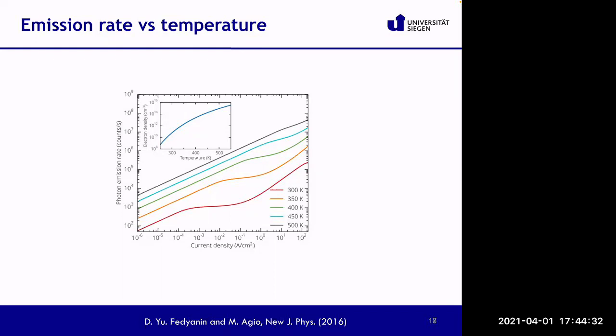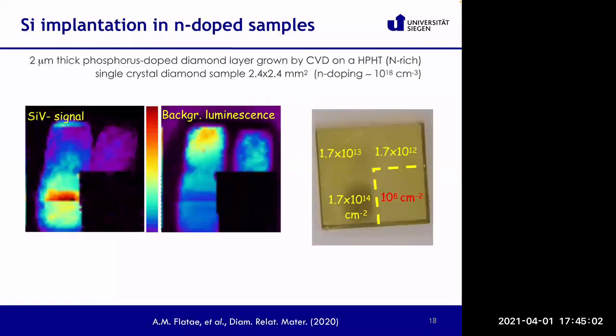So this shows that if you want to do electroluminescence for single photon emission with diamond, you need to work not at cryogenic temperature, but you have to be able to work at higher temperature. And of course, this is a problem because we know that this will not give you a narrow emission line, which is required for example, photon indistinguishability. So nevertheless, this is still open research. And so we decided to also try that.